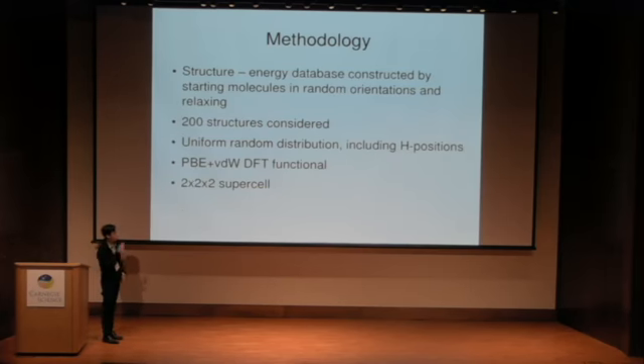So this is my approach to this question. I basically want to sample the low energy landscape. I start off theoretical DFT calculations in random orientations, with the molecules pointing in random positions, and I let them relax to their ground state or close to ground state structures. In so doing, I build up a database of energies and structures. There are about 200 of them, and I start by randomizing the positions of the molecules, including the hydrogen positions, because I want to sample the hydrogen bonding patterns as finely as possible. I've used the PBE density functional with dispersive corrections for van der Waals forces, and this was done in a 2x2x2 supercell.